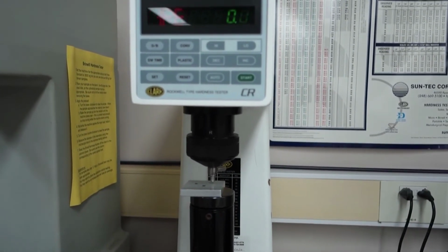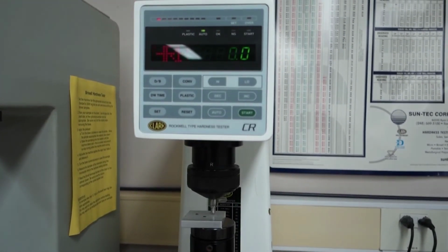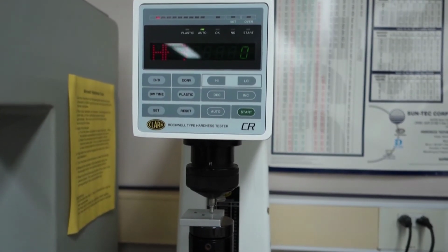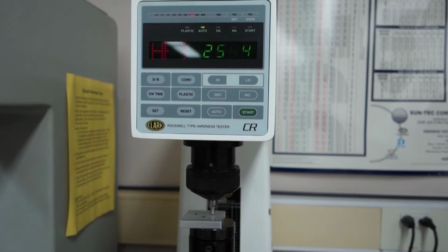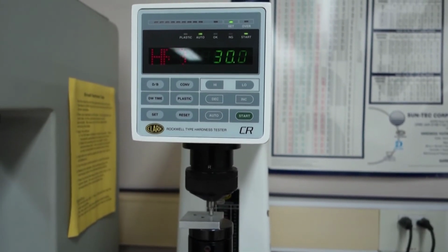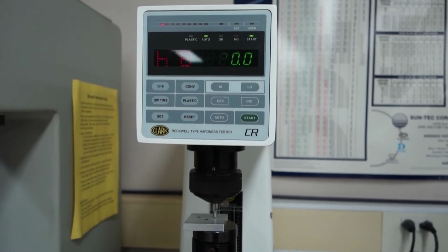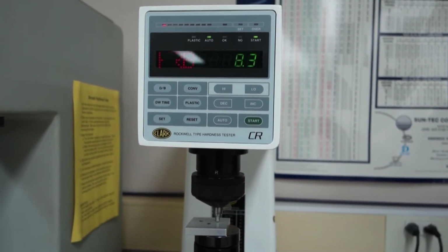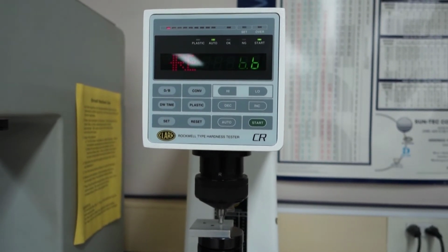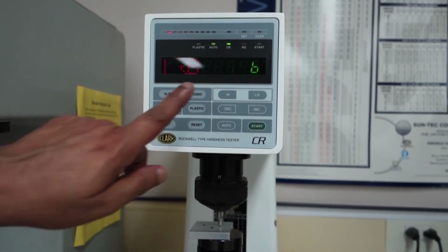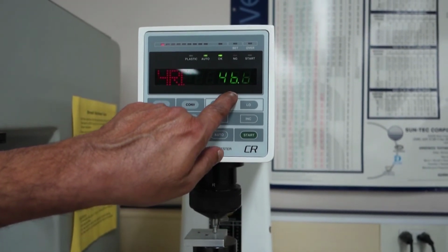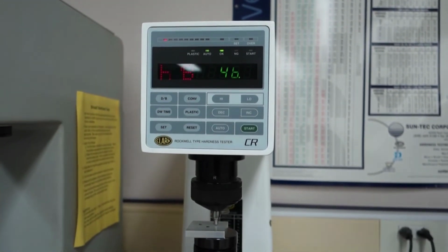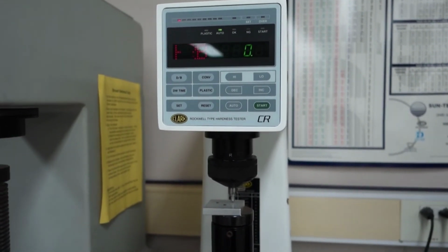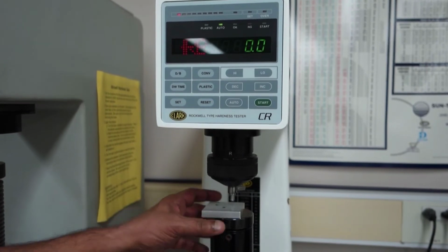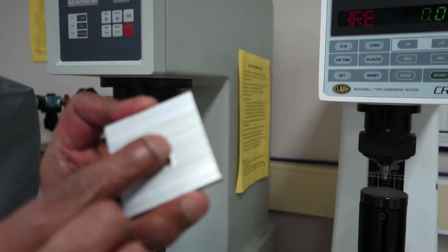I'm going to raise the anvil, and if you watch this band, when the load reaches 10 kg, the machine takes over. So the machine has now taken over. It reset it to 130, which is the baseline. Applying the load now. It has removed the load, and now the hardness reading is displayed as 46.6. I'm going to remove the load by lowering the anvil, and we can see that we have made this indent right here.